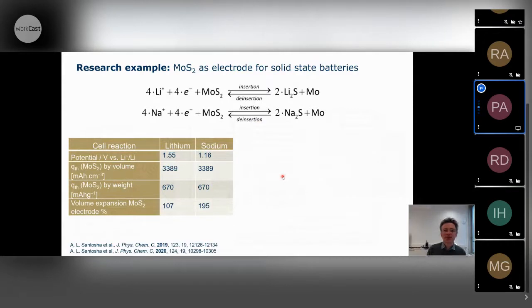This is an example for molybdenum sulfide. Here we have a comparison between lithium and sodium for liquid cells and for solid-state cells. The ideal reaction looks like this, also very simple. You have molybdenum sulfide, and during discharge you form lithium sulfide and molybdenum, or sodium sulfide and molybdenum. The truth is that in between there are a lot of intermediate compounds, and this reaction as written here does not really take place. This is really an idealized way of writing it.